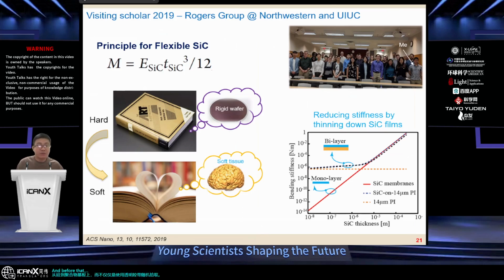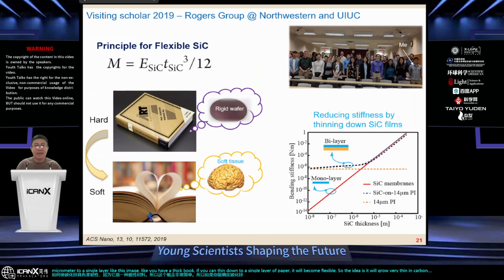And before that, we go back to the fundamental mechanical concept: how to make silicon carbide flexible, because it's a brittle material. So the concept is really simple. If you can thin down silicon carbide from a few hundred micrometers to a single layer, like this image, like if you have a thick book and you thin it down to a single layer of paper, it will become flexible. So the idea is if we grow very thin silicon carbide on silicon, a few hundred micrometers thick, and get rid of the silicon layer and transfer silicon carbide onto a polyimide layer, then the polyimide layer will actually dominate the bending stiffness of the bilayer of silicon carbide and polyimide. And in that case, we will have flexible devices.